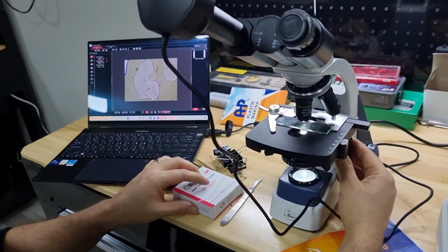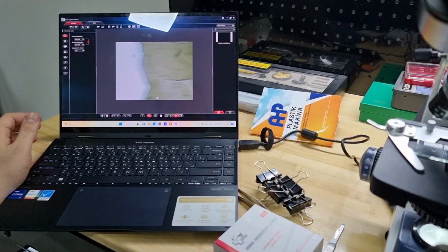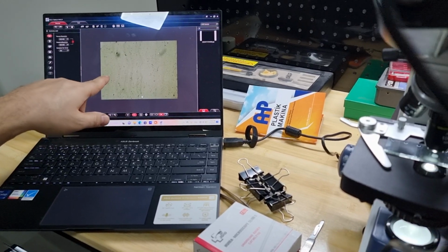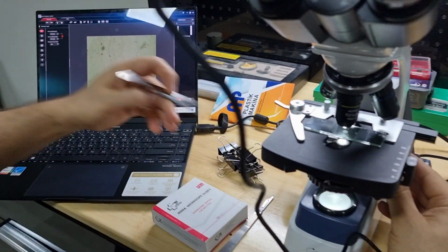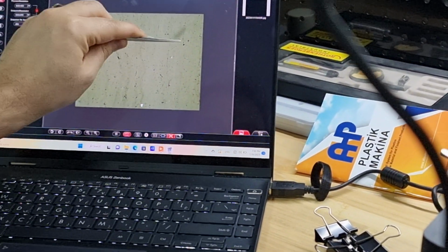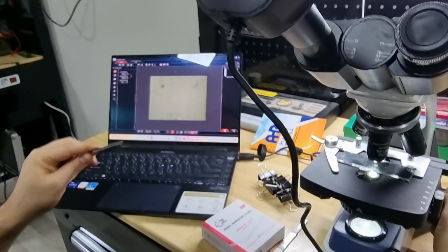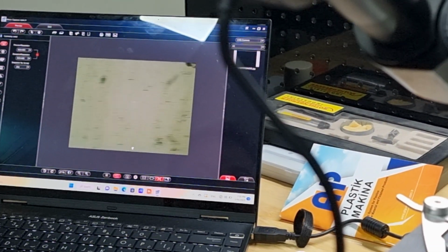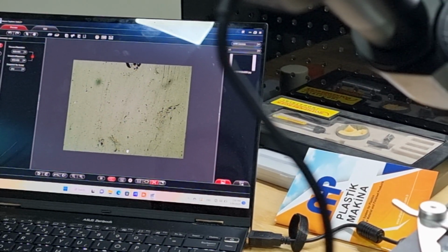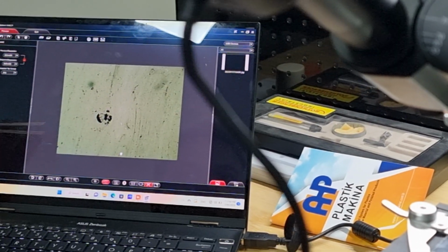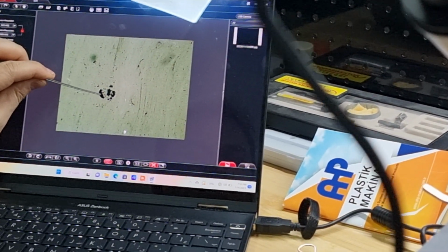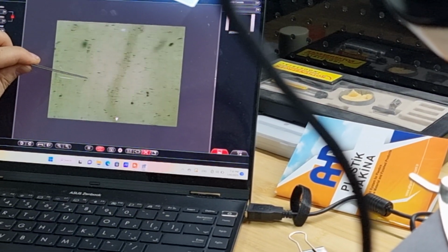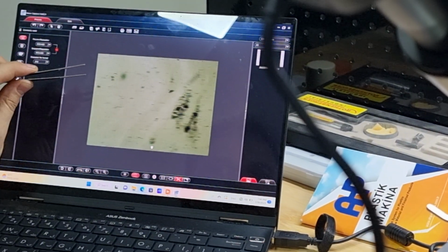You see the pictures here. These are agglomerates. Here you see agglomerates of carbon black. Based on the standard, you need to measure these agglomerates' sizes. The biggest diameters of these agglomerates need to be measured based on the standard. You see, these are bad situation for carbon dispersion, these are the big size of agglomerates that you see in the sample piece. Here as well, you see some big size agglomerates.